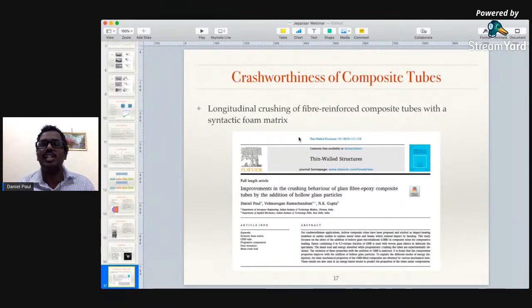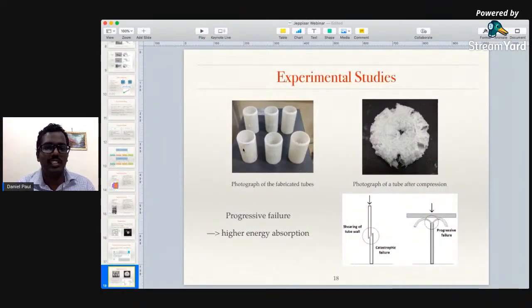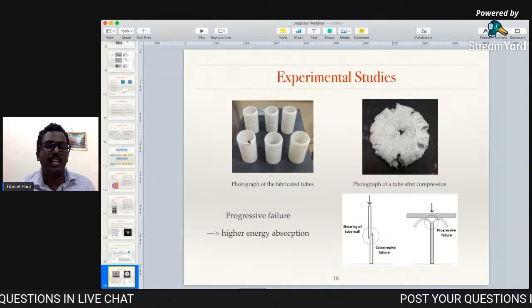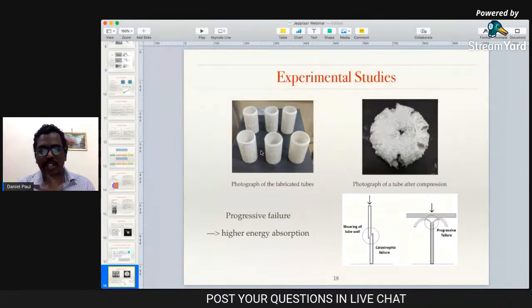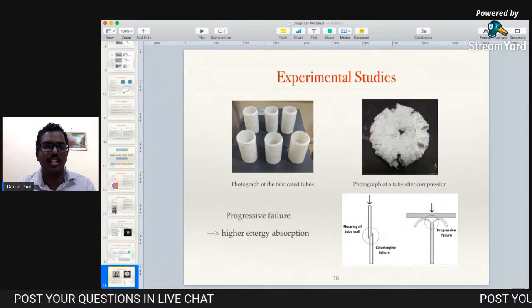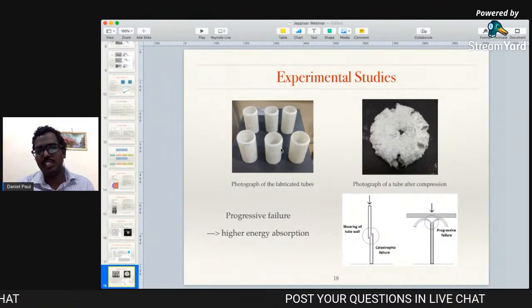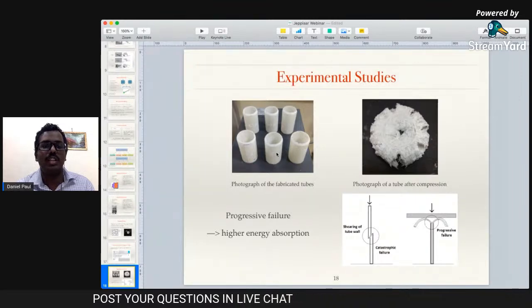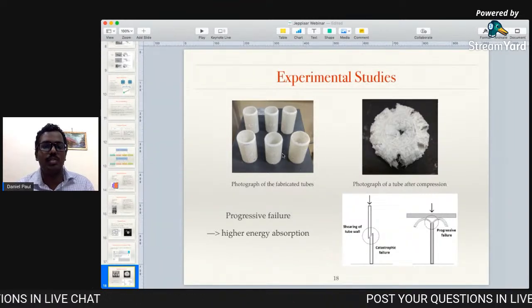Crashworthiness is nothing but, if a car is coming into the market, they test whether it is worthy of withstanding some kind of crash or some kind of energy impact on it. So improving the crashworthiness, or the energy absorption characteristics, of these composite tubes was the first work that we did, and it was published in the journal Thin-Walled Structures. What we did was we fabricated these composite tubes using glass fiber and epoxy matrix, which is a normal GFRP composite, as they call it. And instead of just using epoxy as a matrix, we used these syntactic foams as a matrix. We added glass microballoons along with epoxy in these tubes, and so they stay hollow.